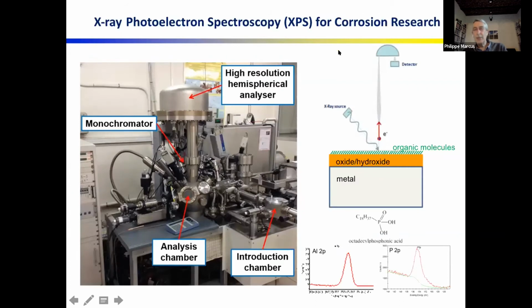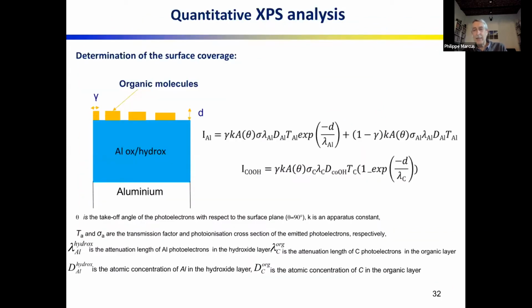So to do that, we used XPS. I think you all know the principle of XPS. We use an X-ray source, photoelectrons are emitted, and we analyze the energy and measure the number of electrons, so we can get an insight on the organic molecule layer, the nature of the oxide under the organic molecules, and the base metal. And this is the equipment that we are using in my lab. This technique is quantitative, meaning that we can not only identify the nature of the surface species, but we can also calculate their concentration. We can also calculate the thickness of the organic layer, the thickness of the oxide. So it's an extremely